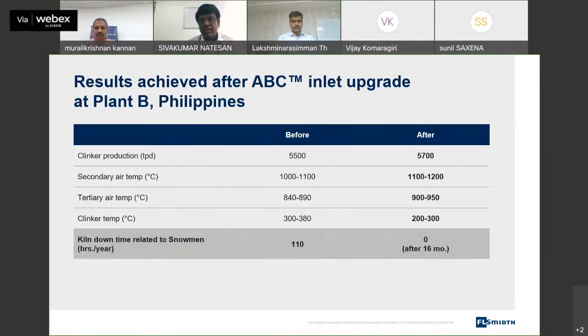This is another plant where you can see that the clinker temperature dropped considerably, with an increase in tertiary air and secondary air temperature. So in general, the ABC inlet not only prevents the risk of agglomeration and snowman, but also increases the heat transfer efficiency, because the plant operation person is conveniently able to handle it. And this was a one-day test result, but over the long term, in a month average, the benefit of the ABC inlet will be much more, because even with varying chemistry the control is better. Hence, the long-term benefits of the ABC inlet on plant operation are visible.